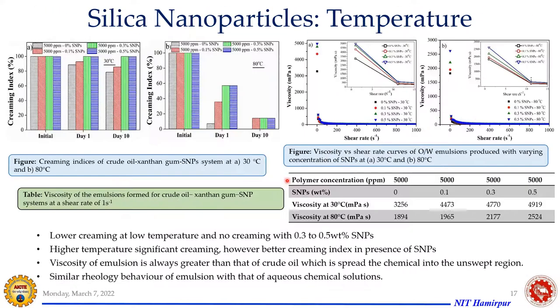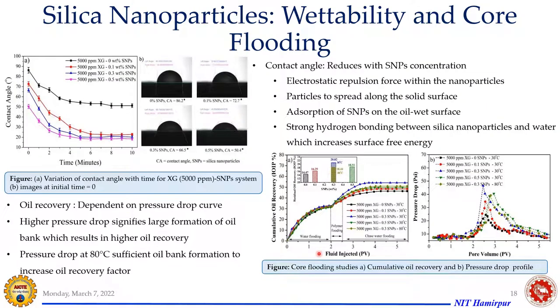There is one more factor affecting recovery at higher nanoparticle concentration, which is the blocking of the rock pores. When we use nanoparticle concentration beyond its optimum condition, it will try to agglomerate and block the rock pore throat. This blocked pore throat will retain the oil, and it could not be produced. So that's why you can see at higher concentration the recovery is decreasing. So the flooding data is also confirming that 0.3 is the optimum condition.